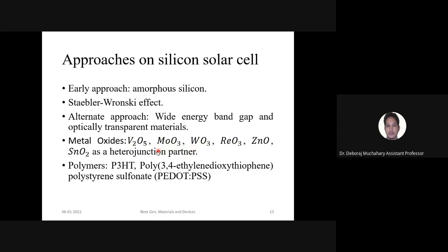But the problem here is that the conductivity of these materials is low. One more parameter we need to know is the conductivity, because whenever light is exposed to the device and electron-hole pairs are generated inside the depletion region or near the surface of the silicon, these carriers need to pass through these materials so that they are collected at the electrode. That depends on the electrical conductivity of the material. Some of these materials have average electrical conductivity, but some have less. Zinc oxide has good transparency but low conductivity. Tin oxide has good conductivity, but its transparency is not up to what zinc oxide has. So these transition metal oxides like V2O5, MoO3, WO3 are used.